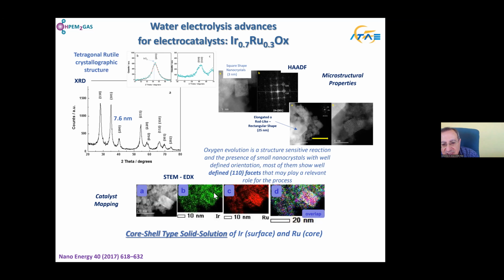But the real situation is, this is a specific case. Usually you have a mixture of several particles, and you also want good distribution of the elements. As an example, ruthenium is inside the particle while iridium is on the surface, in order to achieve good electrochemical activity and also good stability.